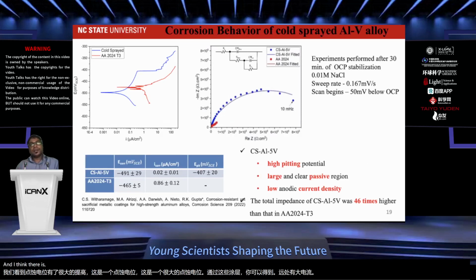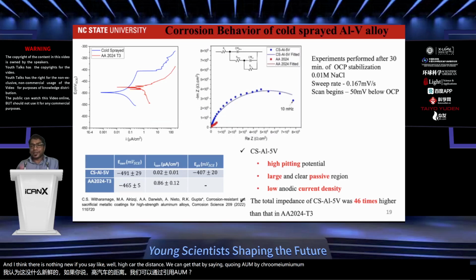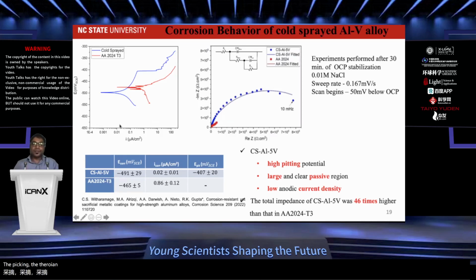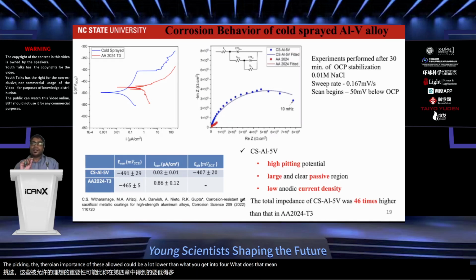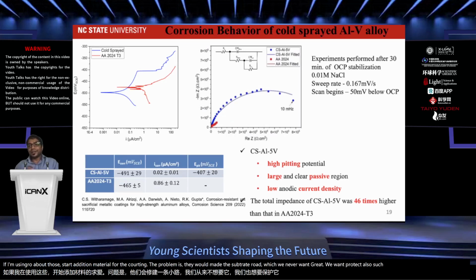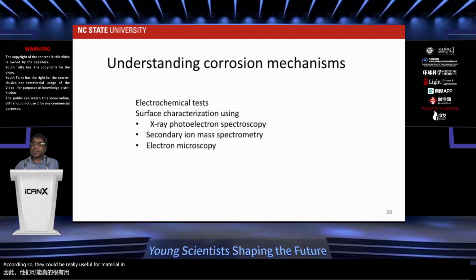And I think there's nothing new if you say, well, high corrosion resistance, we can get that by, say, coating aluminum with chromium or nickel or something like that, right? But one advantage here is that the corrosion potential of these alloys could be a lot lower than what you get in 2024. What that means is if the coating breaks down, these materials could be sacrificial coatings. They could corrode very slowly and protect your substrate. If I'm using nickel or chromium or those corrosion resistant materials for the coating, the problem is they would make the substrate corrode, which we never want, right? We want to protect our substrate, not the coating. So they could be really useful materials in that sense. And there could be a lot of other